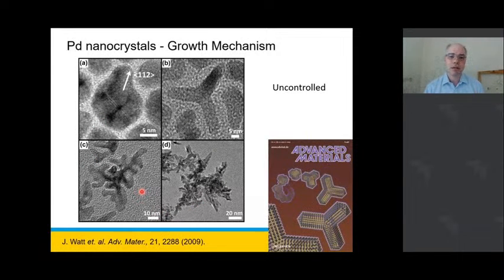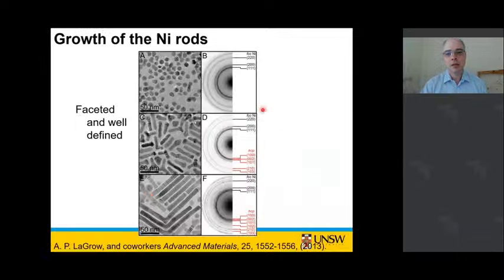So although this is a way to make branch particles and branch structures, because it is so uncontrolled, what you do actually end up with at the end is these kind of structures that don't really have surface facets and don't really have particularly the low index surface facets that we're really after for a lot of catalytic reactions.